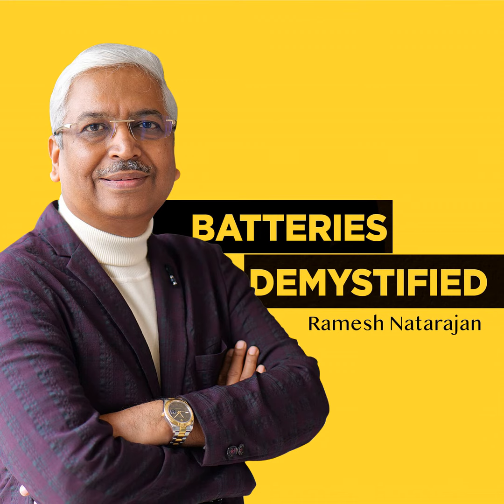Let me now explain the behavior and correlation of plate voltages with respect to the cadmium electrode during the charging process. During the charging process, the potential of the negative electrode undergoes a reversal towards the end of the charge. For a charged cell with a total voltage of 2.70 volts, the positive plate potential is 2.50 volts and the negative plate potential is minus 0.20 volts.